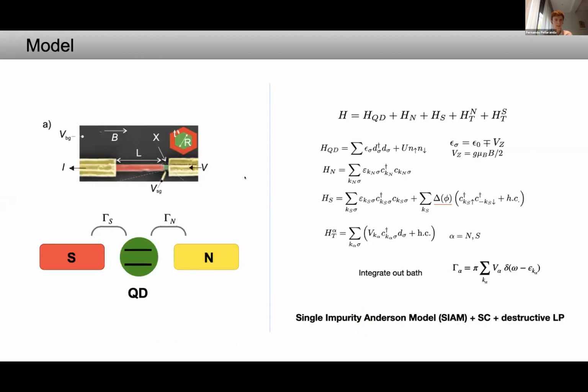So in order to describe the experimental setup, we will use a Hamiltonian as a sum of the following terms: a Hamiltonian describing a two-level system with Coulomb interaction and charging energy U, which describes the quantum dot forming in the tunnel region. Then a Hamiltonian for the normal lead, and another, a BCS Hamiltonian, that describes the full-shell nanowire. Note that here the BCS gap delta is dependent on the applied flux due to the destructive Little-Parks effect. And finally, we have two tunneling Hamiltonians from the quantum dot states to the normal and superconducting leads, which upon integration of the fermionic baths in both leads gives rise to the two tunneling rates, gamma N and gamma S. So this is the standard formulation of the impurity Anderson model coupled to normal and superconducting leads and with destructive Little-Parks effect.